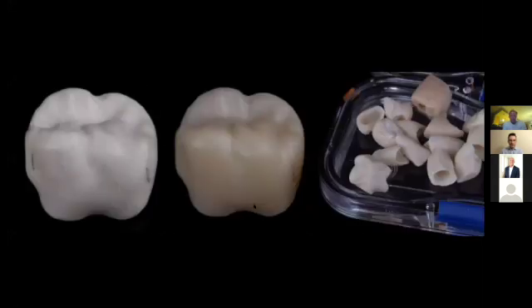This is a picture I took. This whole group of crowns there, I had gone in. We don't have a zirconia sinter in the research lab, but we've got one in the dental school. And so sometimes when I need to make specimens, I'll go and borrow their sintering furnace, and I'll have to program in my own programs. And one day I programmed my own thing, and then I left and forgot to change it back to their original program. And they fired this whole batch of crowns with the wrong sintering fire, and they all came out this white opaque. They look like little Dalmatians, like white and brown Dalmatians.